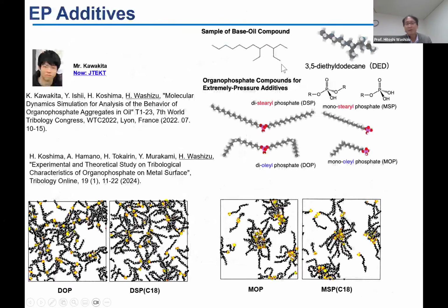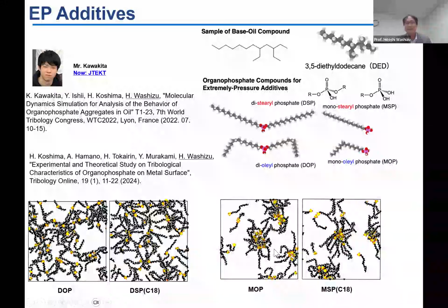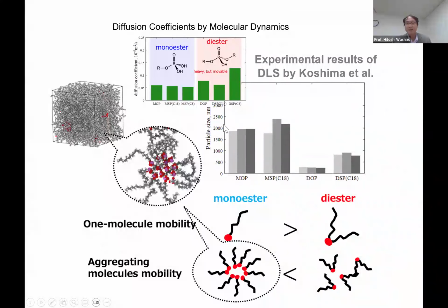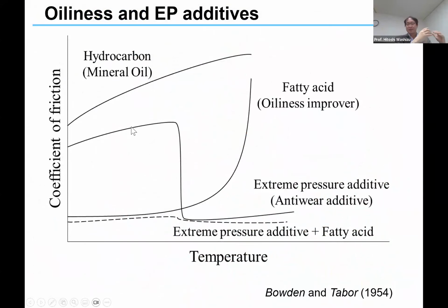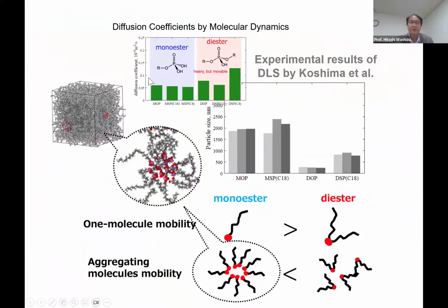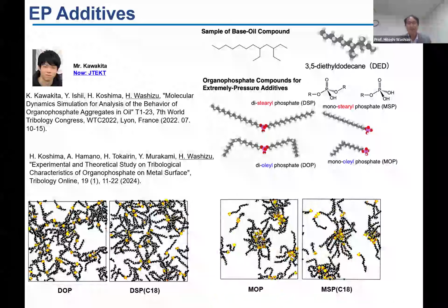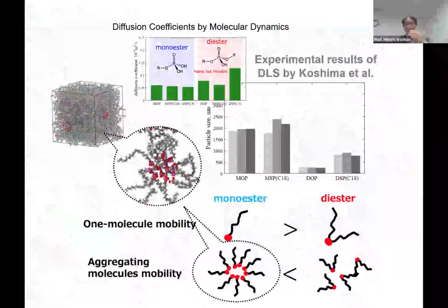What's the difference? So we calculated this. We prepared the phosphate molecules in the base oil, and then we found that they make aggregates. It depends on the molecular structure, but they make aggregates. And the size of the aggregates depends on the additive molecular structure. At low temperature, they are very stable in the oil. So they do not reach the surface, because this is the particle size, and this is the diffusion coefficient, and diffusion is much smaller compared with single molecules. So surface interactions become rare with this kind of phosphate. So I'd like to express that we can distinguish the difference between the chemical structures on the molecular side. Okay, but maybe you may understand.